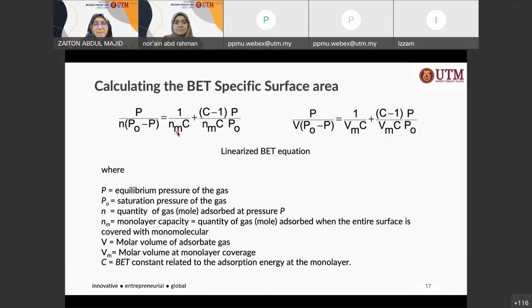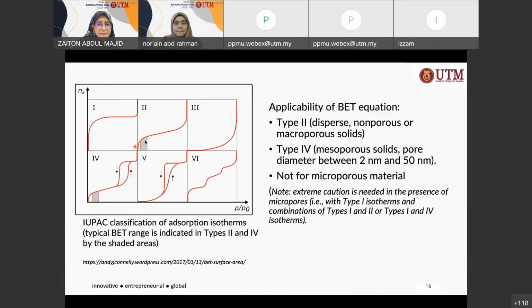Now, even though we say that the BET model takes into consideration multilayer formation, when you determine the surface area, you are still looking at the part whereby the monolayer coverage is complete. For example, if I just go back to this one, this region here, you have a point B. This is the point whereby the monolayer coverage has been completed, and this is the range which you take to calculate the BET surface area.